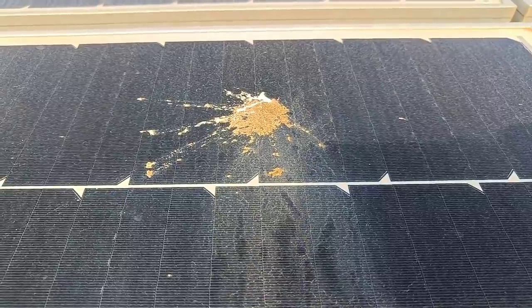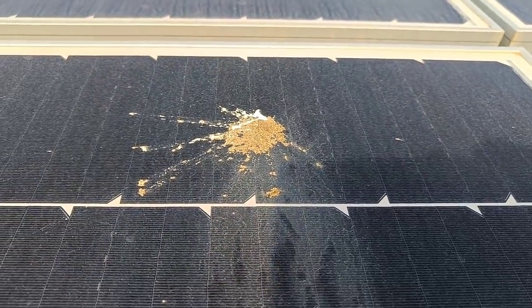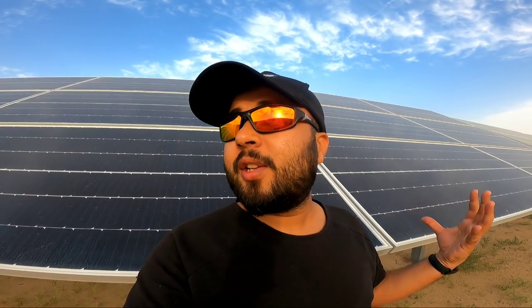No matter how much dust repellent coating you apply, bird droppings will still come. Bird droppings are so hard they don't come off easily and are so acidic that wherever you have applied the hydrophobic coating, it will get damaged. The real problem is not birds — it is that if you are in a city, soiling is very high and soiling is not only dust but a mixture of asphalt, metal particles, and other things. Scrubbing will definitely damage and the nano reflective coating will eventually evaporate under the sun.